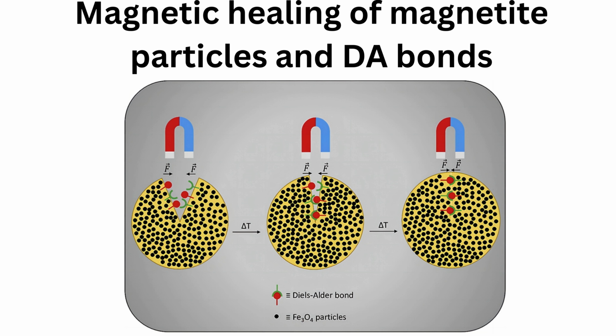Scientists prepared a magnetically initiated self-healing elastomer by incorporating Diels-Alder bonding and magnetite particles into polymers. The incorporation of DA bonding endows the polymer with self-healing properties, with the magnetite particles acting as the driving particles. A magnet was placed at the damaged section of the elastomer and simultaneously heated to enhance the material's fluidity. The magnetic field was utilized to induce electromagnetic effects, thereby stimulating the material's self-healing capabilities, thus facilitating the restoration of its integrity.